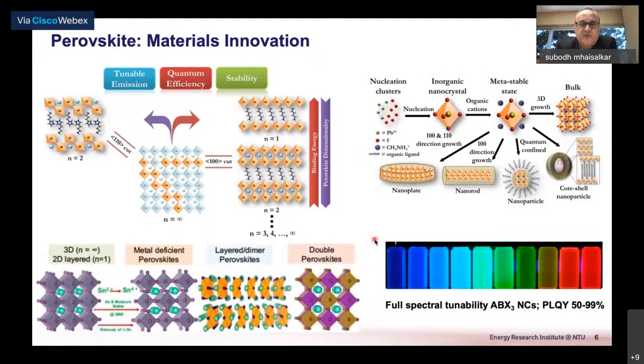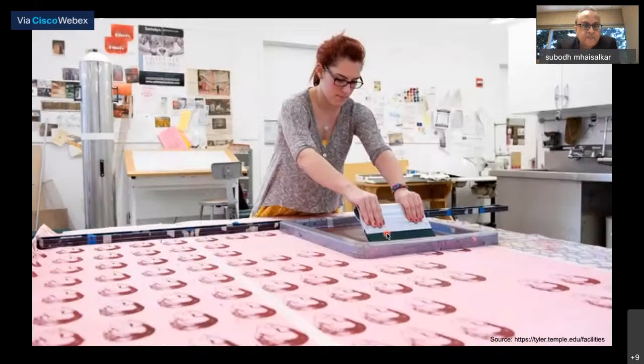Further complexity can also be introduced by the possibility of nanostructuring. You can make perovskites into nanoplates, nanorods, nanoparticles, and even core shell nanoparticles. And this also gives really a full range of spectral tunability, and very high photoluminescent quantum yields can be obtained by these quantum dots or nanoparticles. One of the significant attributes of this is, of course, it can be deposited by very simple techniques like a squeegee printing type, screen printing type technique. And I'll touch upon that a little bit.